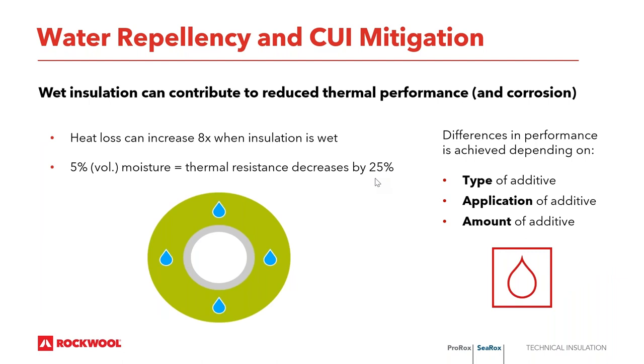So why is it critical to, quote unquote, stay ahead of water in regards to water repellency and wet insulation? To no surprise, I'm sure, to anybody on the call, wet insulation material offers critically reduced performance. Heat loss of the insulation system can actually increase 8 times when the insulation becomes wet, which is pretty significant, right? But another interesting statistic is how much the thermal resistance will degrade when it's wet. Even with just a very small increase of 5% moisture by volume in the insulation material, this can reduce the thermal resistance of insulation by up to 25%, which is very significant.